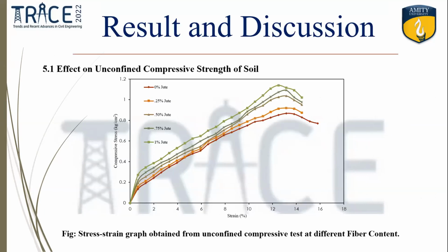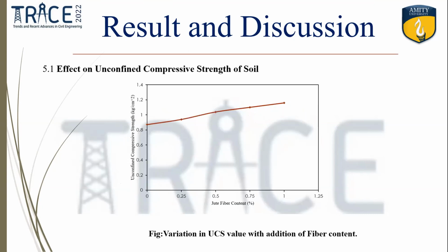These are the results which are obtained from the UCS test. As we can observe from the graphs, as the percentage of the jute increases, there is an increase in the UCS value. Next slide, please. This graph represents the increase in the UCS value with the fiber content. When it is at 0% jute fiber, the UCS value is minimum, that is 0.87, and maximum at 1%, that is around 1.16.